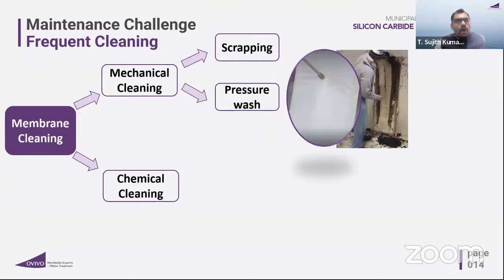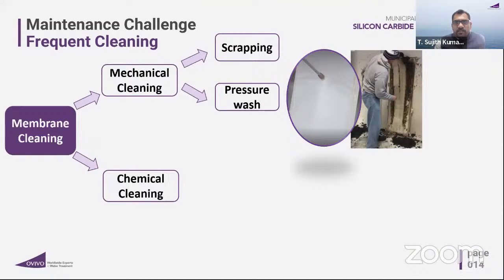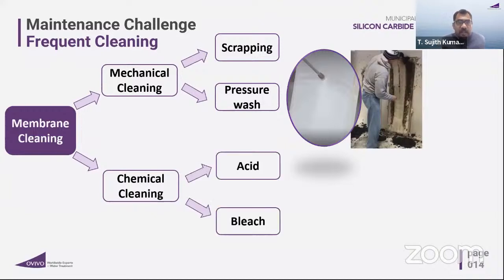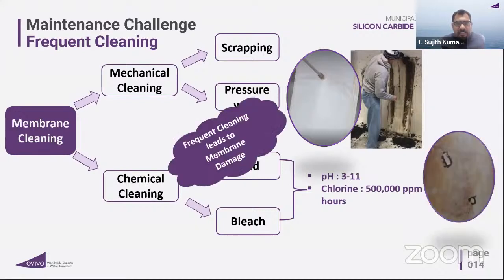Which is very difficult. Or the other option is you need to do the pressure wash, which is not possible for polymeric membrane because there is a pressure limit also. You cannot go more than 3 psi, right? So there is a limit. Or the other option is you go with the acid cleaning and bleach cleaning. Again, you have a limitation of 3 to 11 pH and 5 lakh ppm of the chlorine contact time. As I said, frequent cleaning of any polymeric membrane will lead to membrane damage.